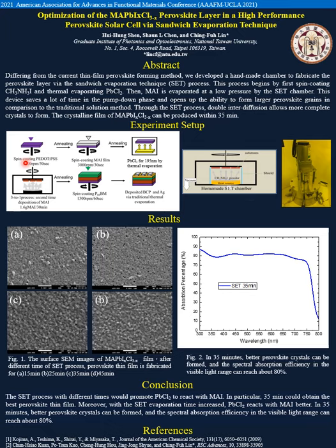This process begins by first spin coating PEDOT:PSS on an ITO glass substrate. After spin coating PEDOT:PSS, we spin coat CH3NH3I, which is called MAI.